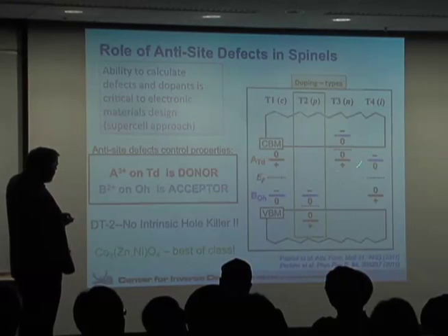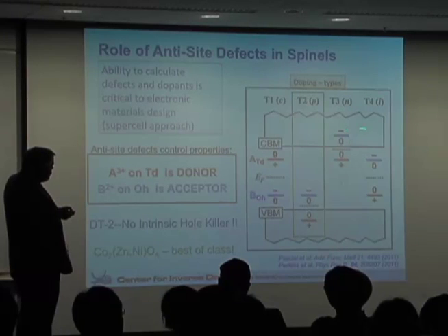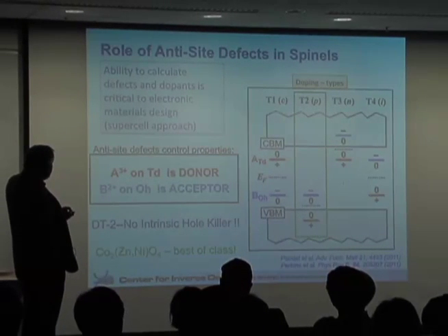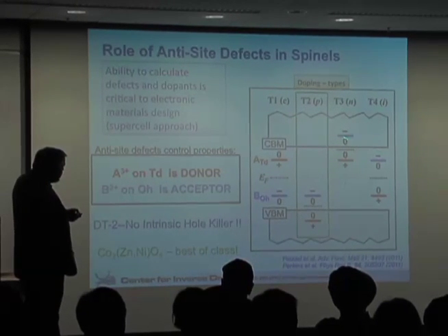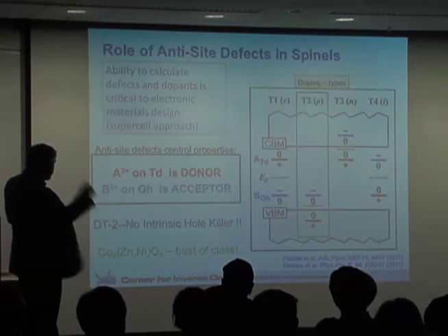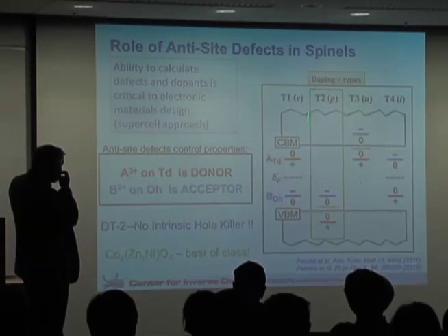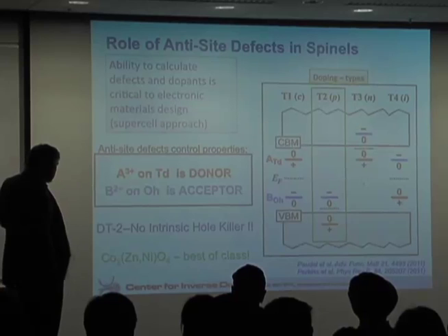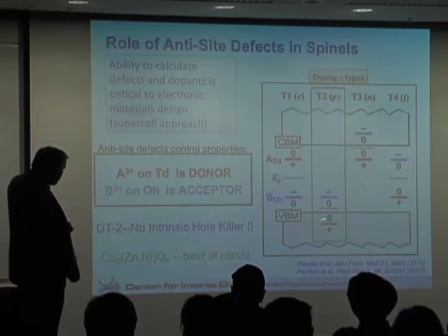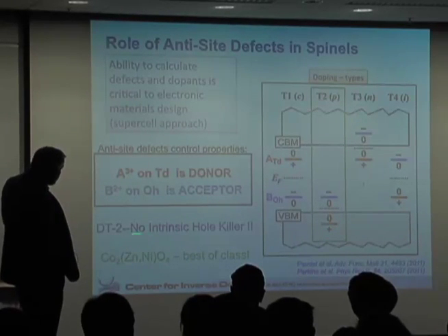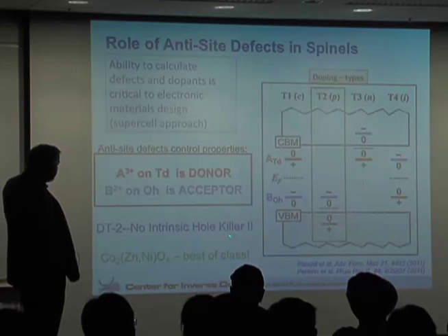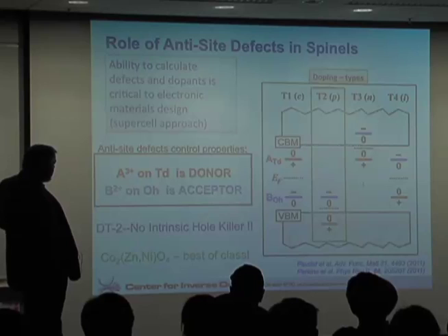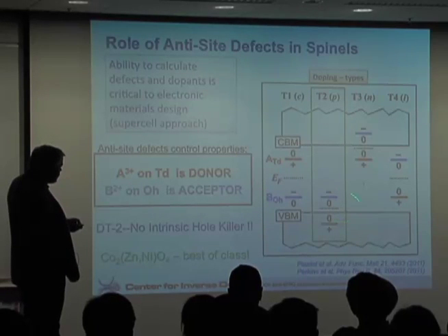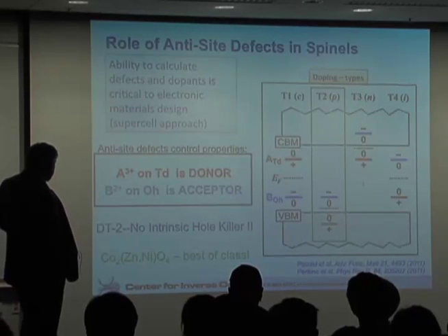The other system that allows you to get to an n-type system is if you could actually bury the acceptor into the conduction band and have the donor there. And so this is a system that we've looked at. We've actually looked across these systems. Because this is electrically inactive, we don't have any intrinsic hole killers here. So if we can get more 2+ cations onto octahedral sites in these spinel systems, we should be able to get pretty significant doping of these materials.